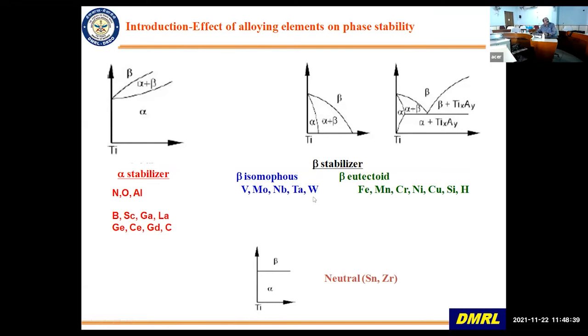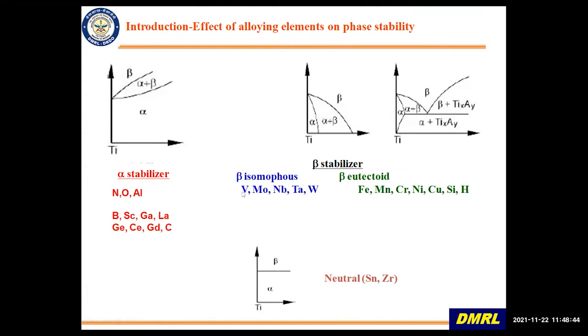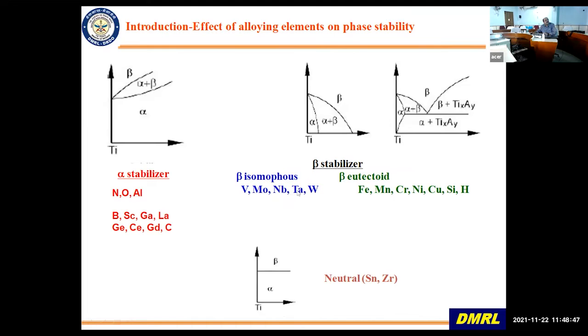And then coming to beta stabilizers, there are two kinds of beta stabilizers. Beta isomorphous, which are these elements: vanadium, molybdenum, niobium, tantalum, tungsten, and then beta eutectoid stabilizers like iron, chromium, nickel, and among the gaseous elements, hydrogen is the element which stabilizes the beta phase. What these beta stabilizers do is they stabilize the beta region, and so they bring down this beta transus temperature line. This is for isomorphous. This is for the eutectoid stabilization.